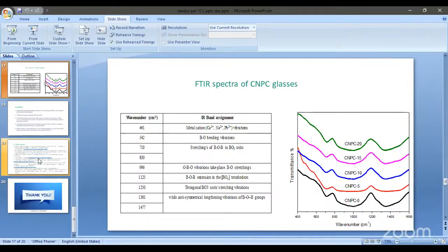Here 461 is the metal cations, and 542 gives the boron-oxygen bending vibrations, and 710 and 830 are the stretching of the BO3 units, and 996 is the oxygen-boron-oxygen vibration, that is the boron-oxygen stretching. And 1125 is the boron-oxygen stretching in the BO4 tetrahedra, and of course the 1250 is the trigonal BO3 unit stretching vibrations. 1361 to 1477 are the antisymmetrical stretching vibrations of boron-oxygen and boron groups.